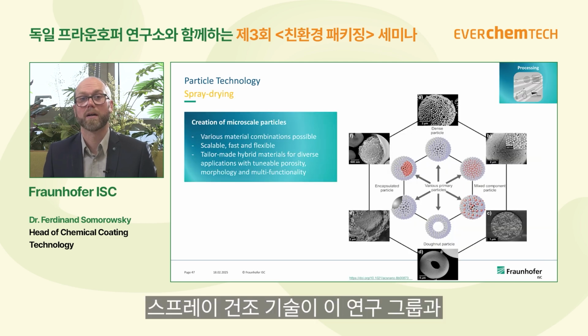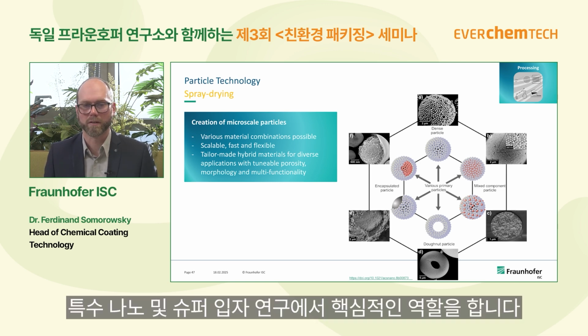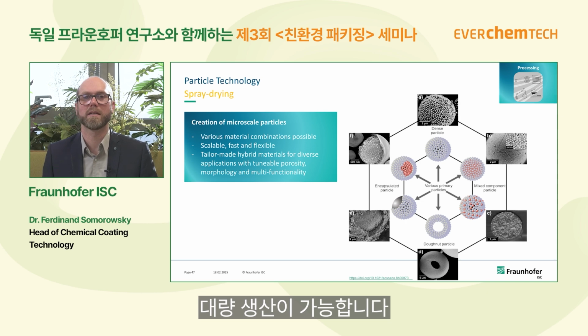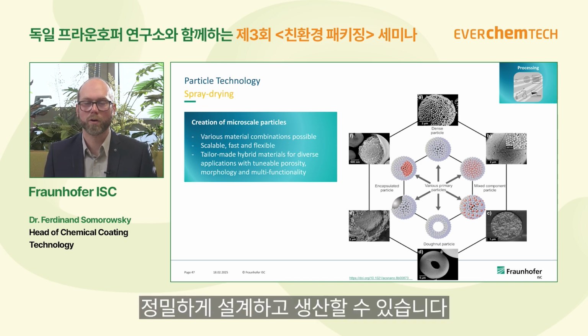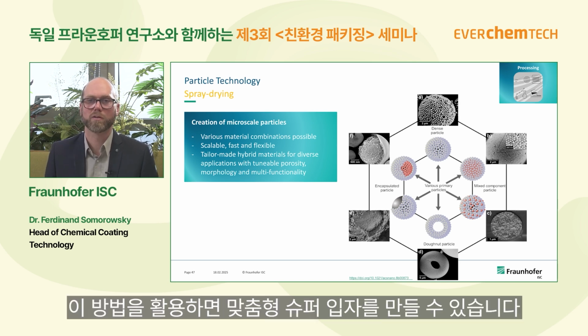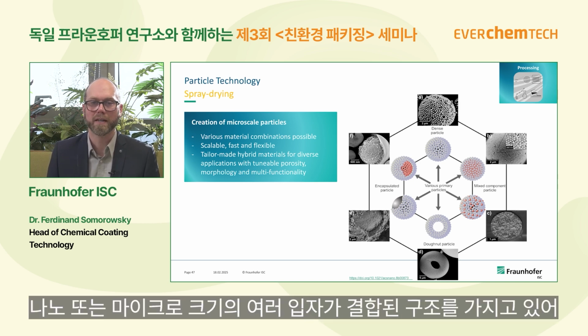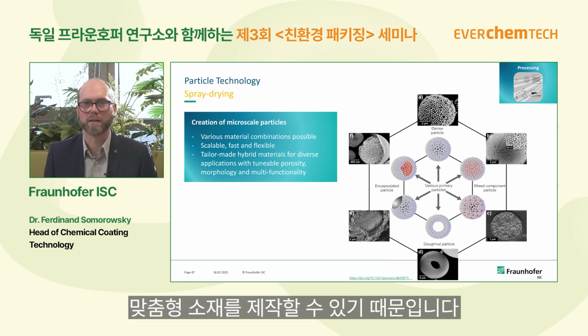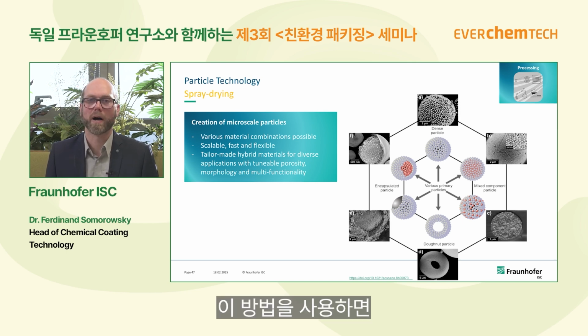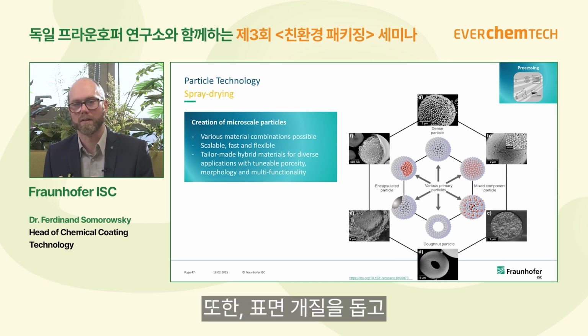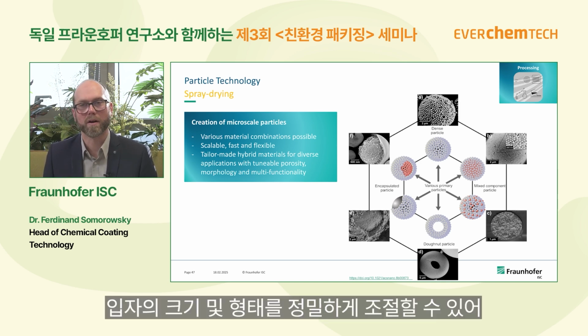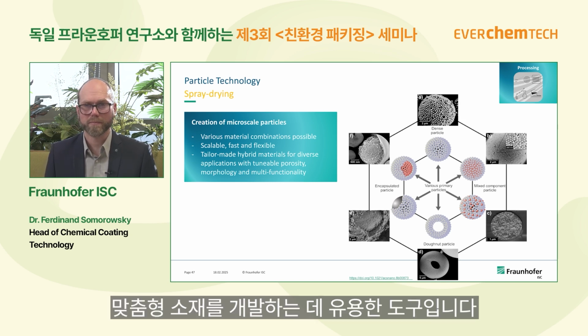When we look at the processing, we have the spray drying process, and I would say that stands at the center of this group, and also of the topic of special nano and superparticles. The spray drying process is easily scalable, and you can produce a lot of material with it. You can really make tailor-made superparticles. We call them superparticles because they are built of several nano or microparticles, and you can really produce tailor-made materials. You can combine different functionalities in one particle, modify the surface, and adjust the particle size and shape very well. That is a great tool to provide tailor-made materials.